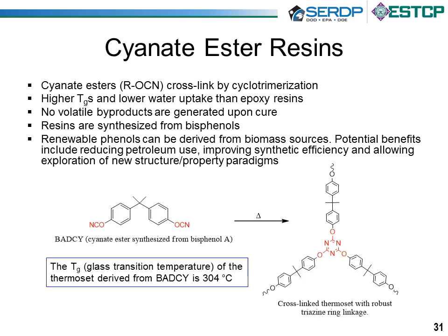The reason we're interested in cyanate ester resins is they have, for example, higher Tgs, and Tg means glass transition temperature, and lower water uptake than epoxy resin. So it's sort of a next generation resin. When they cure, there are no volatile byproducts like water or other small molecules, and that aids in the fabrication of composite parts. Typically, these resins are synthesized from bisphenols, like bisphenol A.